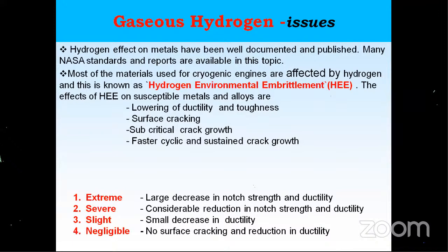But this is different. In India, we don't have any facility to test the effect of gaseous hydrogen. Somebody started in Bombay, but they withdrew because it is not safe. But a lot of data is available from NASA. Like in any tensile testing, you introduce a chamber, fill it with hydrogen, increase the pressure, and see the mechanical properties at different pressures. The result is immediate. The moment you test a material in hydrogen gas, it suddenly becomes brittle. It's not a delay. Many materials have been classified as extreme, severe, slight and negligible, and materials are selected based on that. We call this HEE, hydrogen environment embrittlement: lowering of ductility and toughness, surface cracking, subcritical crack growth, fast cycling, and sustained crack growth. These are the immediate effects.